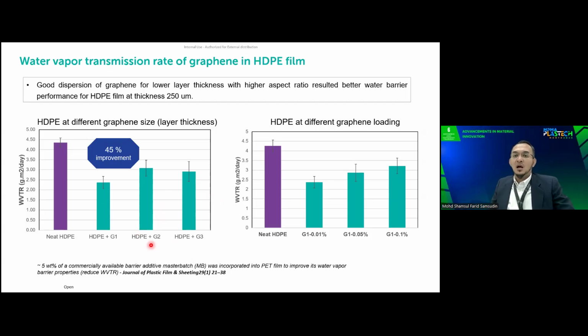And maybe in the thermoplastic industry or other types of coating, to improve the barrier performance, they require quite a number or high loading of the additive. In some of the cases that we studied, published in a journal, some of the additive, the master batch, they use up to 5 weight%. As compared to this graphene, we use very minimum, less than 0.1 weight%, which is only 0.01. So it means that it can give benefit in terms of reduction of the additive if we use this graphene.